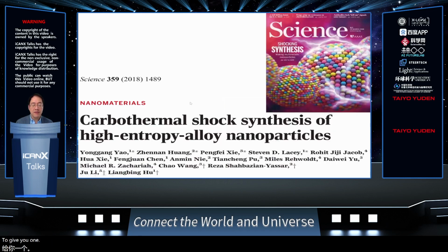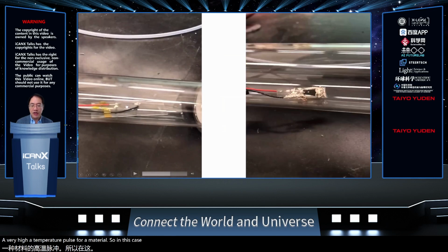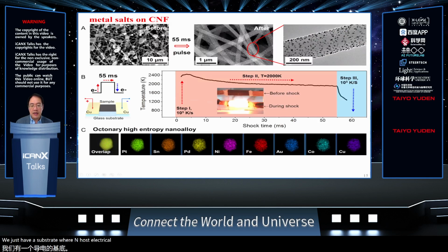To give you one example, a few years ago, Professor Liangbing Hu and we collaborated in trying to understand what happens when you apply a very high temperature pulse to a material. In this case, we just have a substrate where a pulsed electrical current is passed through it. And within tens of milliseconds, the temperature rises to more than 2000 Kelvin. And then we can also cool down very rapidly within tens of milliseconds.